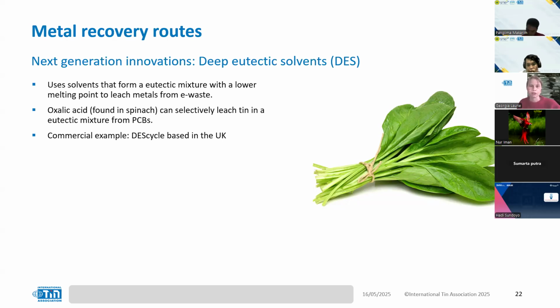In academic literature, for example, academics have used oxalic acid, which is found in spinach, hence the picture of spinach on the presentation, which is able to selectively leach tin from PCBs within a eutectic mixture. They found that they were able to leach 92% of the tin from the PCB in just an hour at 80 degrees Celsius. A commercial example is a UK-based company called DES Cycle. They are looking to commercialize the process, and they raised over 10 million in Series A funding to do this.